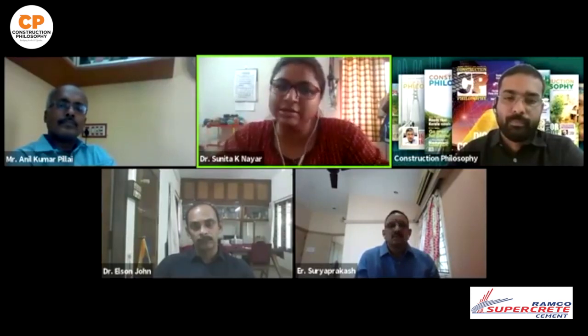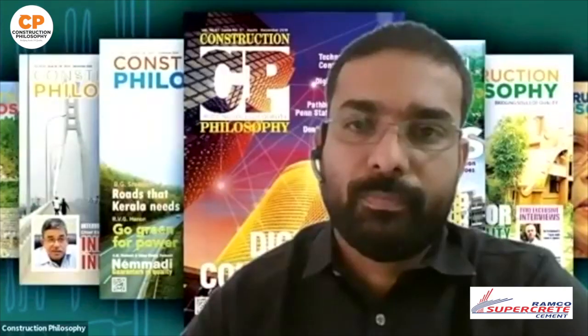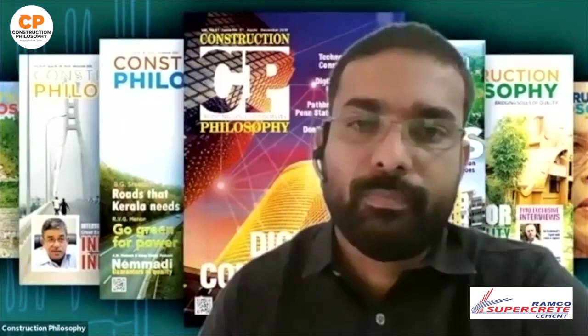That's what I think is the starting of the discussion of Dr. Elson, where he says that prevention is better than cure. So you are talking about after the crack occurs, or how to prevent cracking? After the cracking itself. Yes. So I think there are a lot of grouting techniques which are being marketed by many manufacturers. Most of these are very good techniques. You are talking with respect to concrete cracking that has occurred, no? Yes. If it is due to corrosion, then it is a serious issue. You have to actually remove the corroded bar, insert another bar, and then only you have to repair the structure. So it depends on the problem.